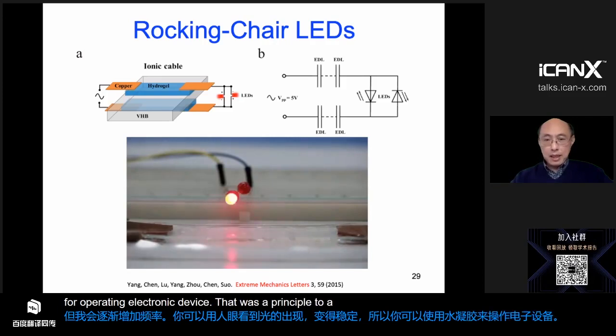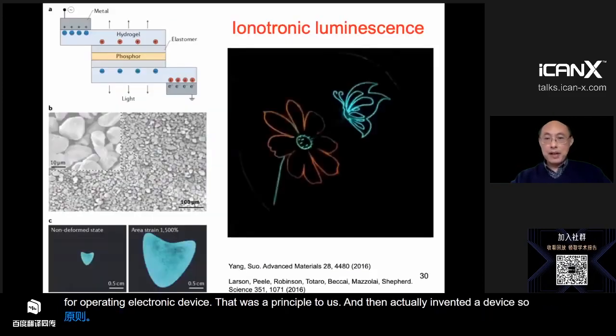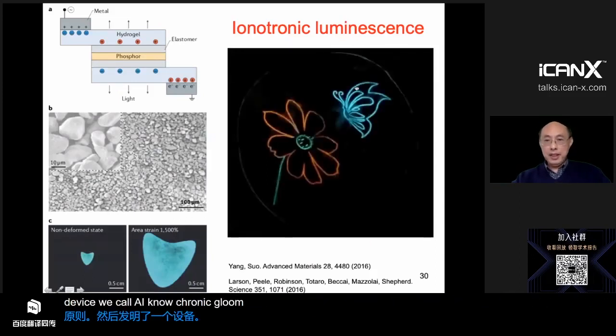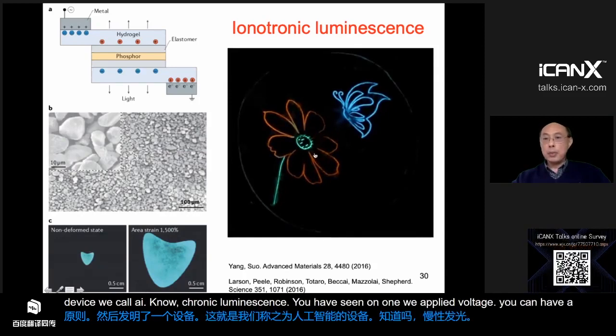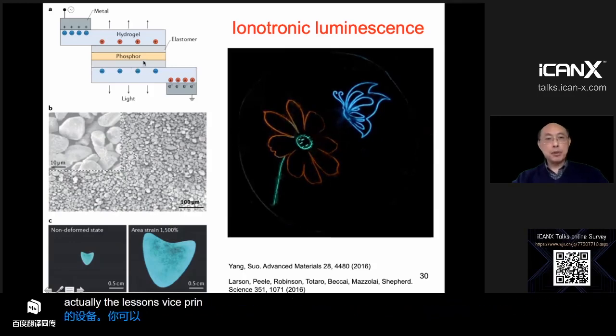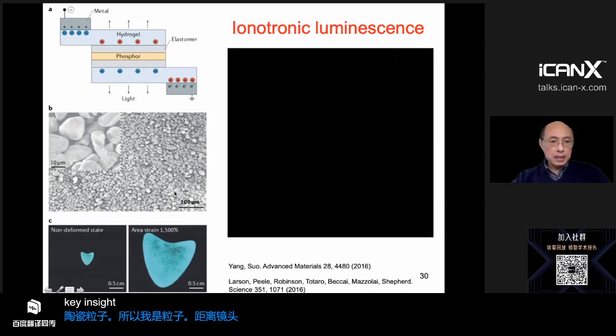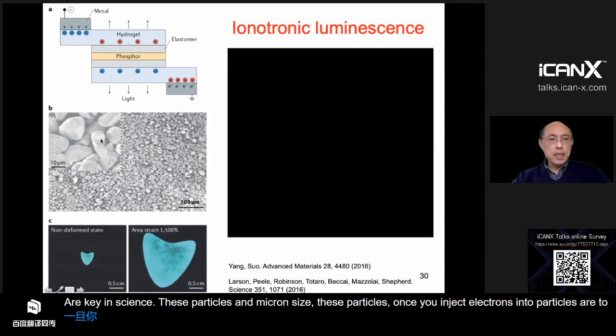And then we actually invented a device. So here's a device we call ionotronic luminescence. You can see when we apply voltage, you can have electroluminescence. The device principle is like this. So here we have a phosphor in the middle. The phosphor is electronic material. It is just a ceramic particle. Ceramic particle here is about 10 micrometer in size. These particles, 10 micron in size. Once you inject electron into the particle, the electron is meant to meet with a hole and generate light. So this is called a phosphor.